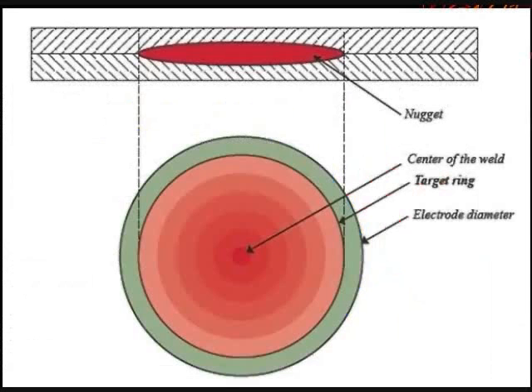From the data we collected, we can build a model of this weld, and I drew up a picture that I call the target ring. The inside of the target ring area, the center of the nugget, is always the hottest, and I call it the center temperature. It is called a target ring because we want to weld something close to that size. The target ring diameter is generally 1 millimeter smaller than the electrode. And the outside, the green area, is the electrode diameter.